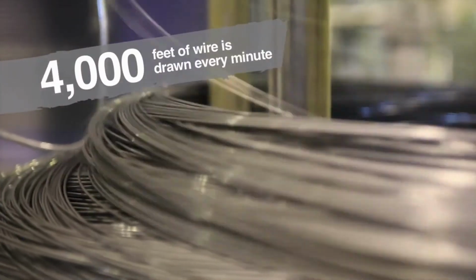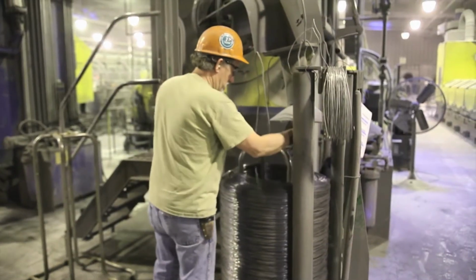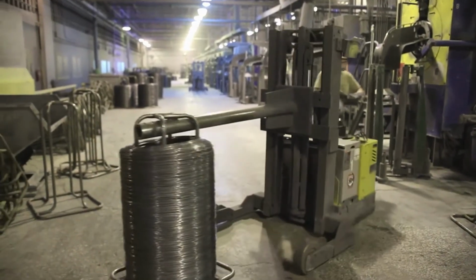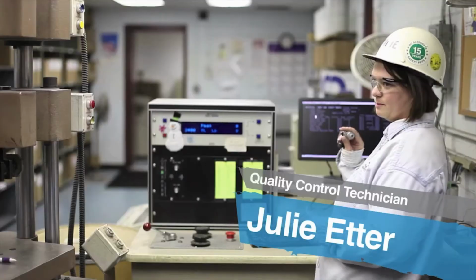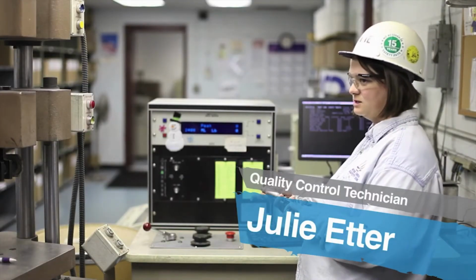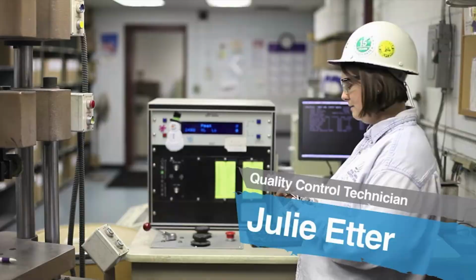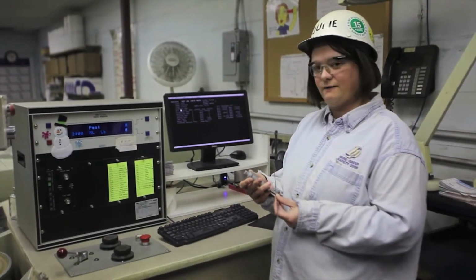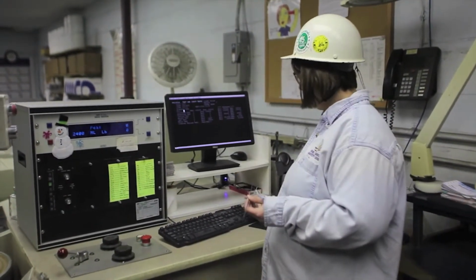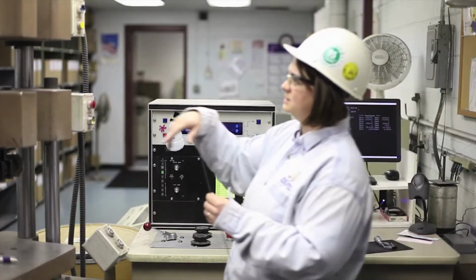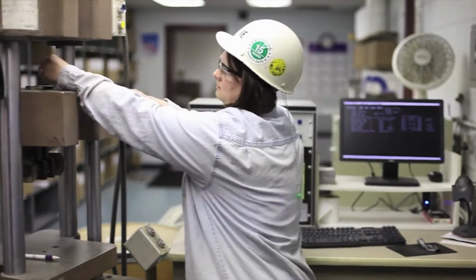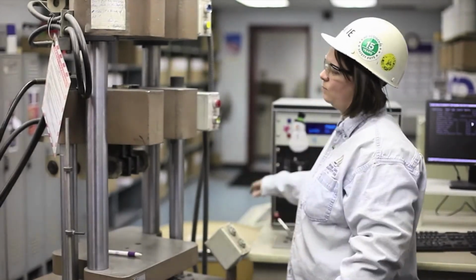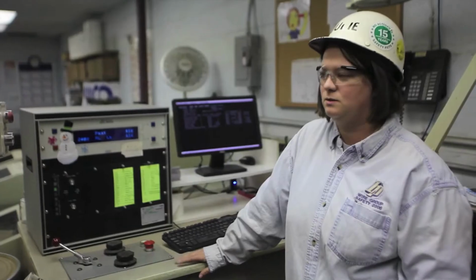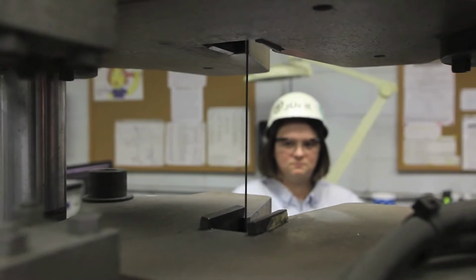Once the wire comes off the machine, the operator will cut it, take a sample. He will do some testing on it himself. Another sample goes into one of our testing labs. I pick up the samples about every 20 minutes. I take a micrometer that is calibrated for each individual tester, and I mic it all the way around, trying to get the high and the low. Then I put that in, and then this is a pencil tester, and so it pulls the wire apart, and that tells you the break load, which is the strength of the wire.